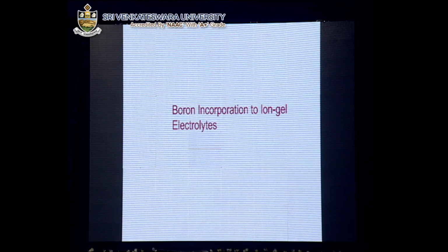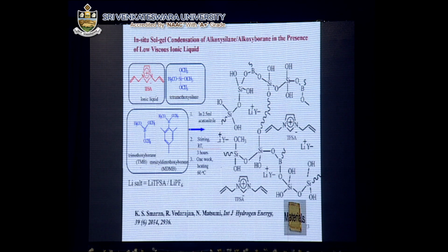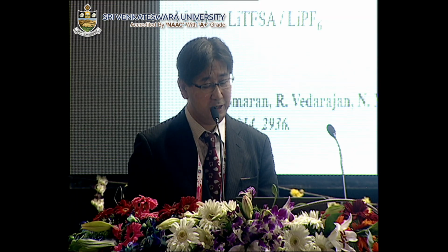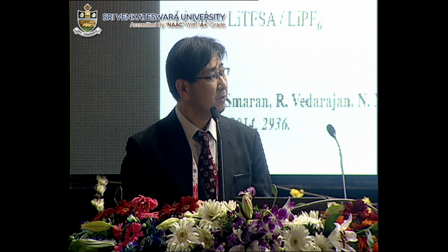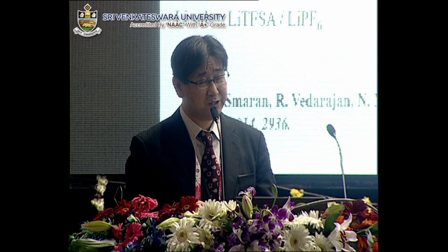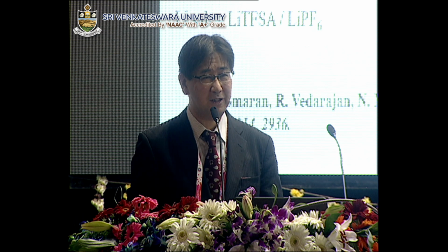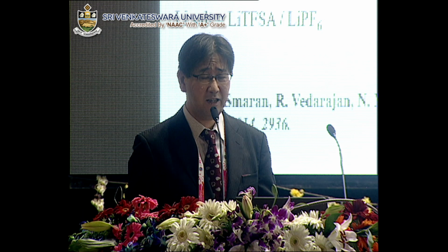And the next topic is the boron incorporation into the ion gel electrolyte. The design of the organic-inorganic hybrid electrolyte is a promising approach in designing highly non-flammable and thermostable electrolytes. And here, such a class of material was successfully prepared by means of in situ sol-gel condensation in the presence of a low viscous ionic liquid.